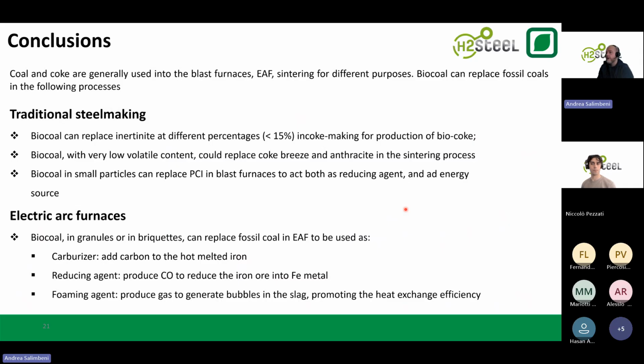So biocoal can replace fossil coal in the coking process at a maximum of 15%, as a pulverized coal at 100%, and in the sintering process the same. In electric arc furnaces, biocoal as well as fossil coal can be used as a 100% alternative as carburizer, as reducing agents, and as foaming agents.